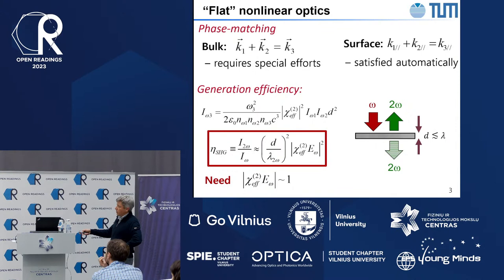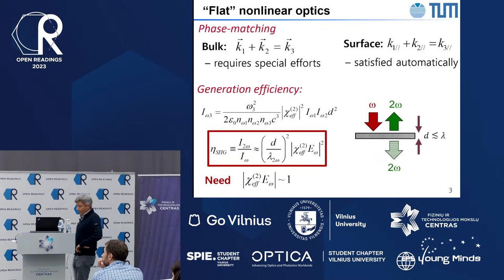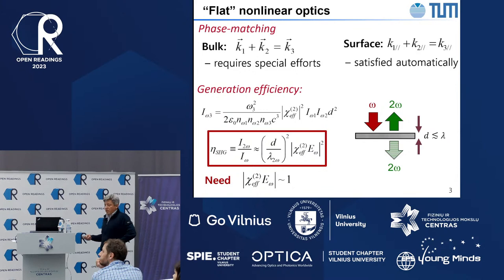And again, similarly to the previous slide, you see that if D is of the order of lambda, if you are sub-wavelength, then chi2 times E has to be of the order of 1 in order for the structure to be efficient. So you need this value, and if you want to limit yourself to some practical levels of intensities, let's say kilowatts or maybe up to a megawatt per square centimeter, you quickly realize that this effective chi has to be 10,000 to maybe 100,000 times larger than that available by nature. So the question is, can you build nonlinear crystals which would have orders of magnitude higher nonlinearity?